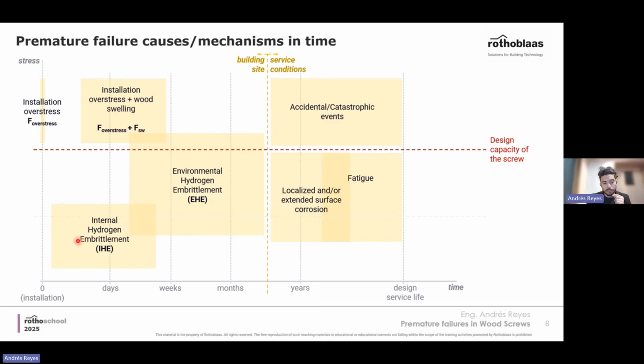One of those would be internal hydrogen embrittlement. We will talk about this in more detail, but it happens from hours to days, could even be weeks, but generally from hours to days after installation. So we're talking about a premature failure where the load on the screw is a lot lower than the design capacity of it.